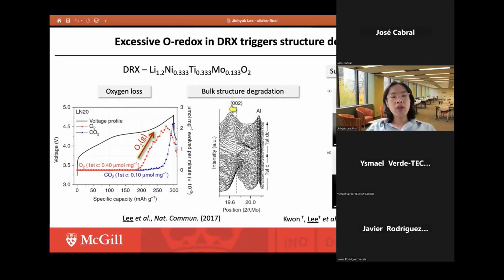And now if you look at the left curve, we are looking at the gas evolution upon first charging. And in this profile, the black one is the first charging curve, and the red curve is the O2 gas evolution. Upon first charging to above 180 milliampere per gram, we see a significant amount of O2 gas detected from this cathode, meaning that there's an irreversible oxygen loss coming out of these materials to change the overall composition. And this happens because the oxidized oxygen tends to be unstable in this oxide lattice. So instead of staying in the crystal structure of the cathode, they rather leave to the electrolyte. So that's one evidence of the side reaction.